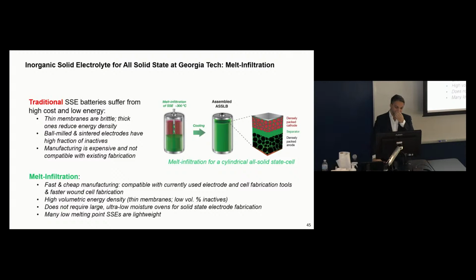And so we thought, okay, it would be nice if we can use maybe solid electrolytes to prevent some side reactions, maybe that would offer better safety, but that would be fully compatible with conventional lithium-ion battery production, right? If you have, let's say, solid ceramic sheets, right, to try to sinter it is much more difficult. But what if you have electrolyte that may be liquid at moderate temperatures, maybe at 100 to 300 C it's liquid because it has a low melting point, but it is a solid at room temperature or at operational temperatures. And so we found quite a few interesting electrolytes that can do that.